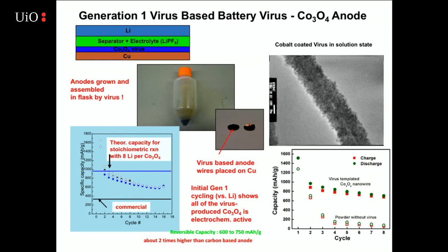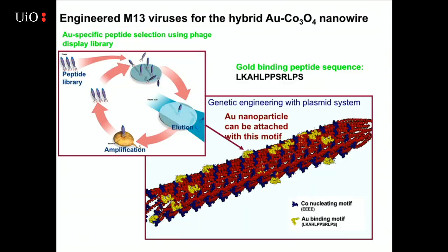This is looking at what it looked like grown biologically, and this is what it looked like made out of a powder under the same conditions, room temperature, room pressure, kind of synthesis. And so it wasn't great, but we had a reversible capacity of about 600 to 750 milliamp hours per gram on our first go at it.